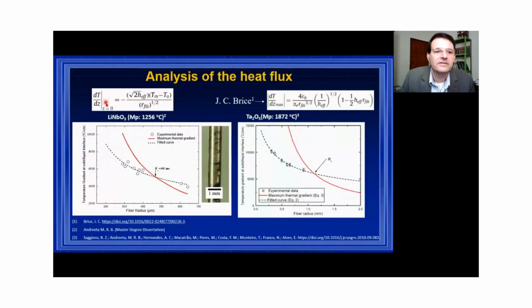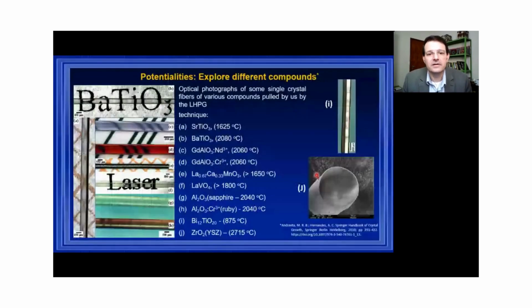So here we have two examples, lithium niobate and tantalum oxide, where we can see that the maximum diameter is exceeded only for a fiber radius greater than 460 micron, okay? And for tantalum oxide it is a little bit higher, about 1.1, the radius of the maximum diameter that you can produce without cracks. So these are some crystals or materials that we can produce in our lab, and you can see that this technique is very versatile.